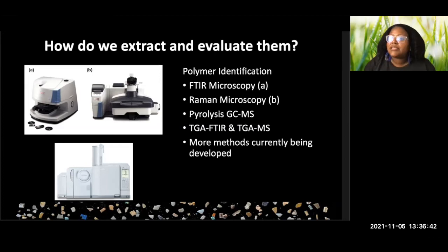Which is great. However, we're often met with size limitations for evaluating the microplastics, with 50 microns for FTIR microscopes and 10 to 20 microns for Raman. Another thing with FTIR is that it's not really the best at identifying cellulosic fibers or microplastics, whereas Raman is better for that. But one thing to note with Raman is that a really brightly colored microplastic can cause some potential hindrances. One thing that is also not possible using FTIR or Raman is identifying the additives that are in these plastics. So you can't really effectively say what kind of effect it might have in whatever matrix you found it in.